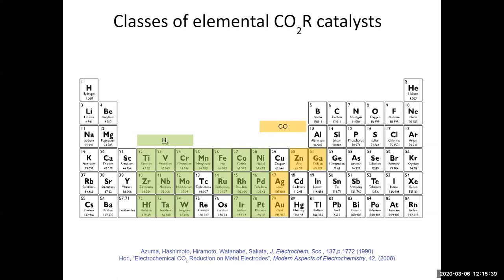If you use zinc or gallium or gold or silver, you have a lot of CO production. You can make formate with titanium or lead or tin. And the only one that's halfway interesting for C1 or C2 products is copper. And so this is interesting because this isn't a matter of finding the next best element, right? We already know what the elements are going to do.